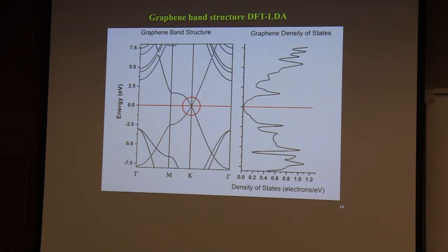So it's a good exercise, if you have already started with calculations, it could be good to calculate graphene. Sometimes you may not get exactly this, you may get a gap, and you should try to choose more k points in your calculations and you will succeed. This is the density of states that shows you have a semi-metal, a zero gap semiconductor.